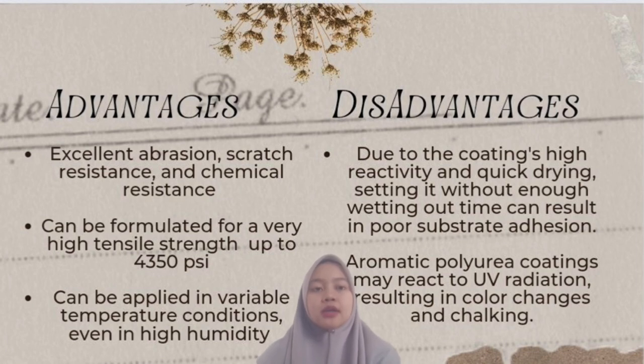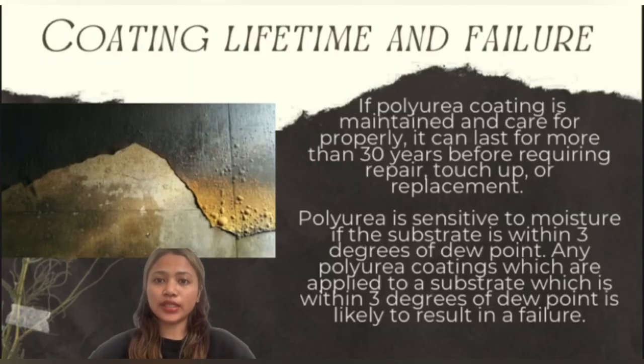Further disadvantages of polyurea coating are due to the coating's high reactivity and quick drying. Setting it without enough wetting out time can result in poor substrate adhesion. Aromatic polyurea coating may react to UV radiation, resulting in color changes and chalking. If polyurea coating is maintained and cared for properly, it can last for more than 30 years before requiring repair, touch-up, or replacement. Polyurea is sensitive to moisture if the substrate is within 3 degrees of dew point.